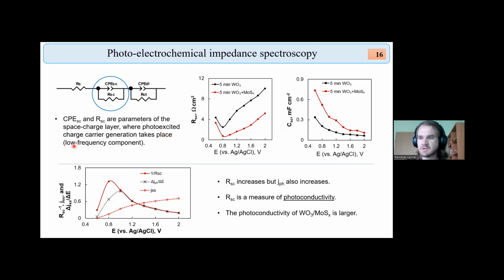The equivalent circuit is shown here. And it has, again, two components, a high-frequency component, double layer and charge transfer capacitance and resistance. But more important are the space charge layer capacitance and resistance. In the theory of photoelectrochemically performing materials, the space charge layer is the near surface layer where the generation of photoexcited charge carriers takes place. That is to say, it is the region where light penetrates into and electron and hole pairs are generated. The electrons move towards the back contact, and the holes move toward the electrolyte where they can participate in a photoelectrochemical reaction.